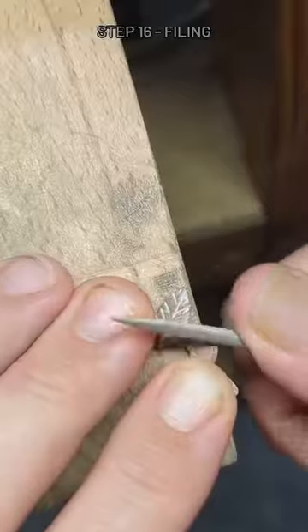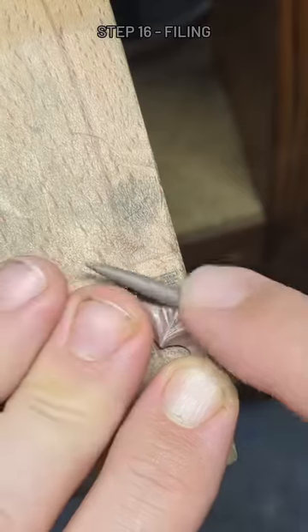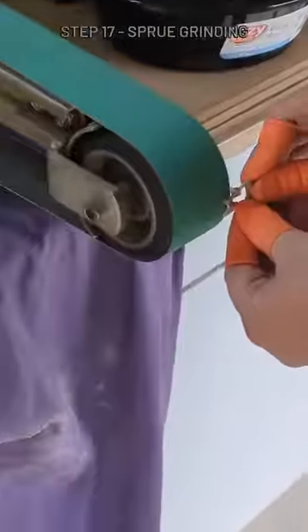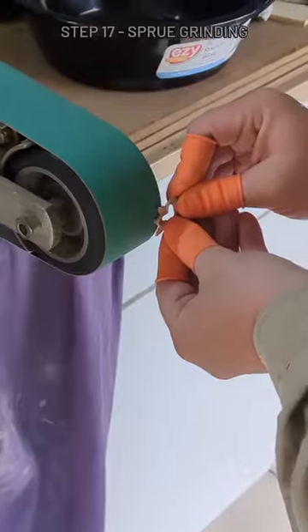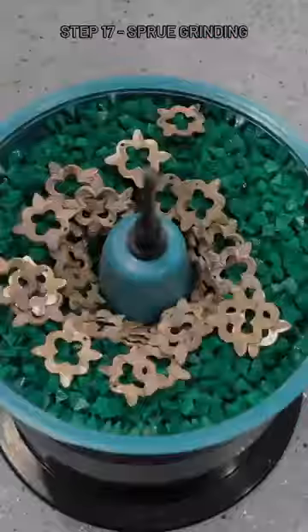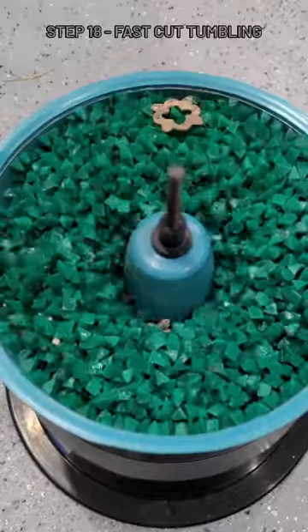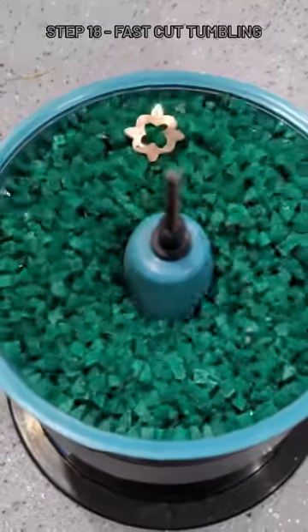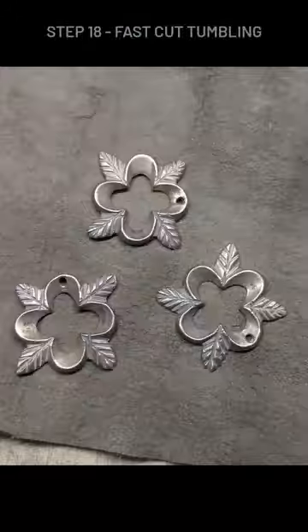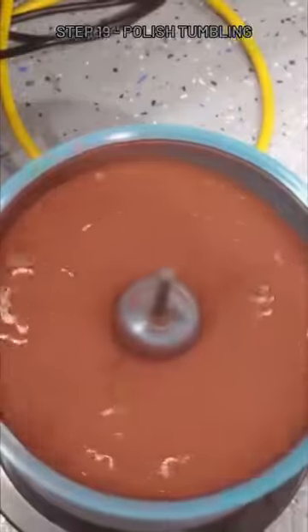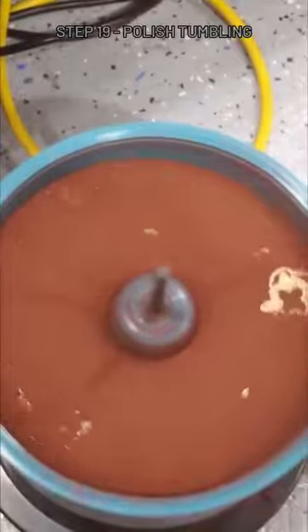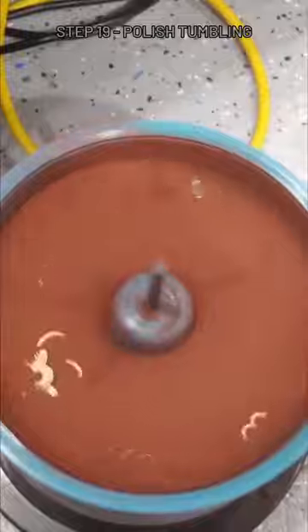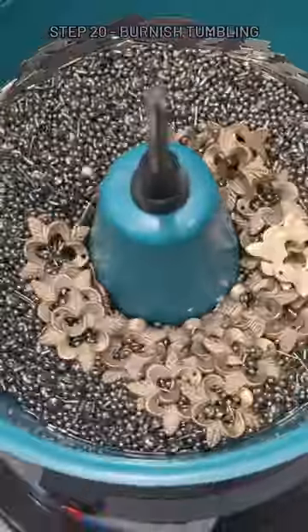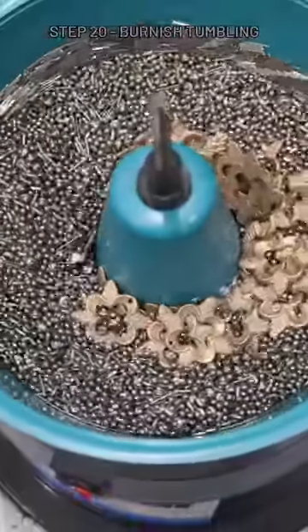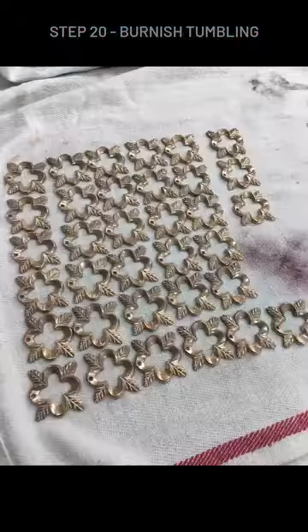Then they get a quick once-over with a file to remove any sharp edges, corners or flashing. The remainder of the sprue is ground off, and then they go into the vibratory tumbler with some abrasive media for a 6-hour tumble. This gives a rough polish on the brooches, and then they go into a 24-hour tumble in a walnut shell media with an iron oxide abrasive. Another couple of hours in the stainless steel burnishing media, and the brooches have finished their mass production polishing